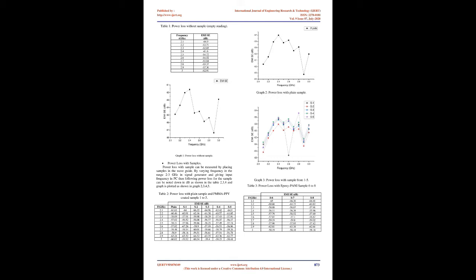The purpose of using triamine hardener is that epoxy is a thermoset polymer; once it is mixed with the hardener, it acquires a three-dimensional network with a rigid structure which cannot be broken by any means. Mix slowly so that no air pockets are formed, for 30 minutes. The resting time should not exceed 30 minutes, else it will become a hard mass and cannot be poured